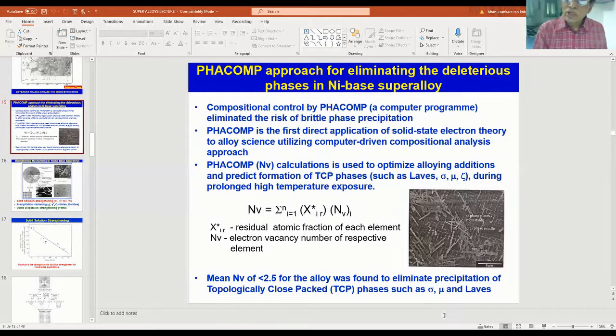So that is the way it is taken care of by the PHACOMP approach, which is nothing but a computer program. While melting is going on, the composition of the melt will be monitored, and the composition is controlled, and that eliminates the risk of brittle phase precipitation during service. So this is a very, very important approach to control the composition against deleterious phase formation.